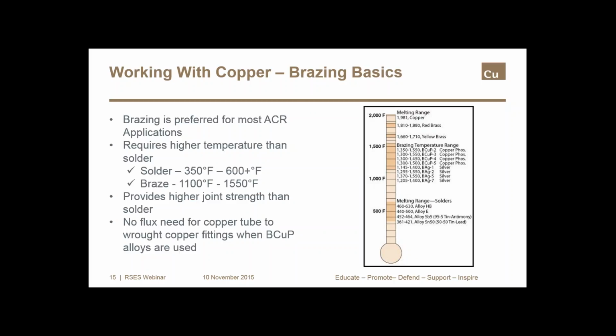We're going to turn our attention now to joining methods, and we're going to start with brazing. Brazing is most common in air conditioning and refrigeration applications, and that's for good reasons. It's a fast process. It makes a strong, leak-free joint. Compared to solder, brazing is done at much higher temperatures. Brazing requires filler metals and capillary fittings. And when brazing copper tube to wrought copper fittings, it does not require flux because the phosphorus in the filler metal does that job. However, when other metals are brazed, fluxes are typically required, and it's critical that the correct flux is used.